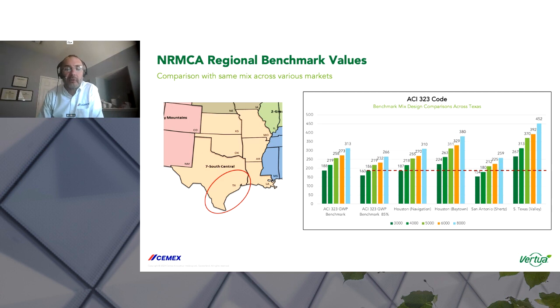So what we've done here, just to show you how it can vary, is we took the ACI basic standard mix that they say is the average of all mixes, and we've calculated the GWP that goes with them, and here are the benchmark values. Then we actually created EPDs for each one of those mixes in 4 of our plants in Texas. And what we can see in Houston on the west side, we can pretty much make it. It's fairly easy. It's close. On the other side of Houston, where we have imported cements and imported aggregates, it's a little bit more tough.